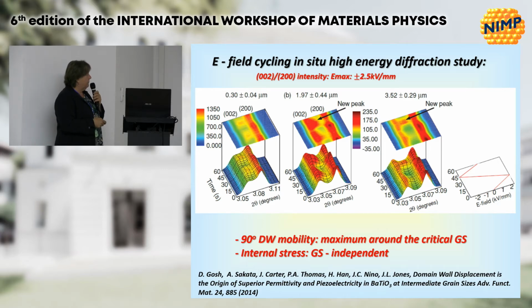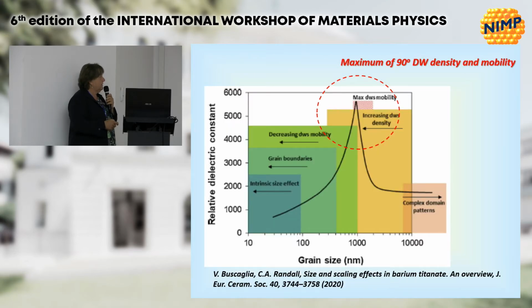I would stress the paper of the group of Jones, because they have shown that in a range of grain sizes they have chosen around the critical size of 1 micrometer, they found that internal stress as determined by diffraction analysis is grain size independent, or the same, while by analyzing the interplay between the peaks 002 and 200 under the application of hysteresis loop cycle fields, by applying this field in situ and analyzing the structure under a high energy source, they concluded, as I said before, that domain walls are the origin of this maximum. Okay, so this is the accepted interpretation concerning this maximum.